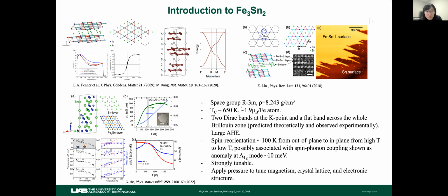lattice. Especially this flat band, based on this model here, it's because of this specific Kagome lattice. On this Kagome lattice, you have the Bloch wave function alternating in sign across the 6 vertices of each hexagon, and that leads to destructive interference outside the hexagon. And that gives you this flat band across the whole Brillouin zone.